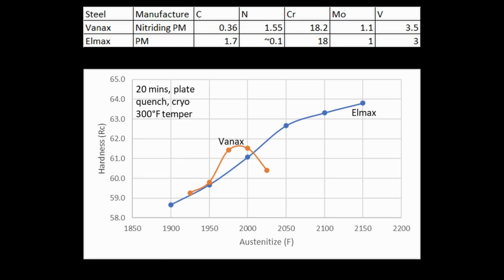So again, we have the case where the Elmax, the carbon version, gets much harder. I heat treated it up to nearly 64. It might be able to get to 64. I was just doing a simple set of heat treatments. I wasn't really trying to optimize for anything. But again, the Vanax peaked out around 61 and a half, and then it drops down.